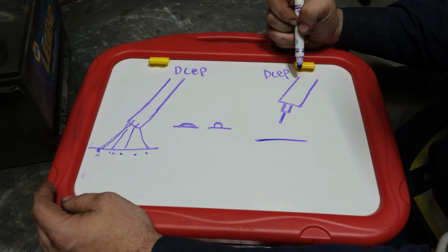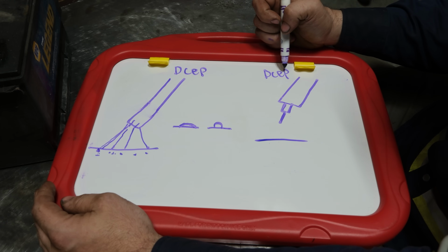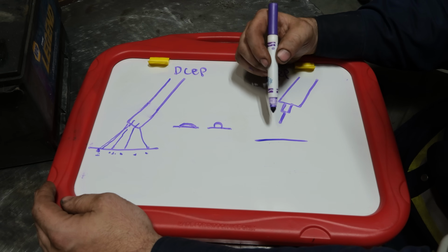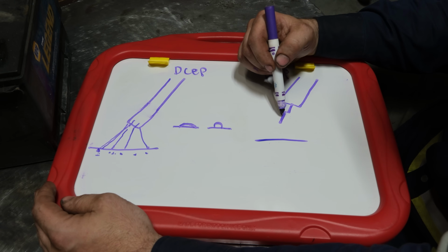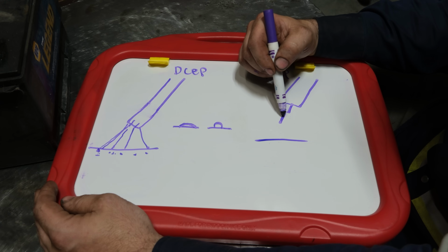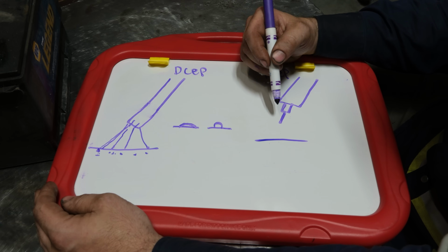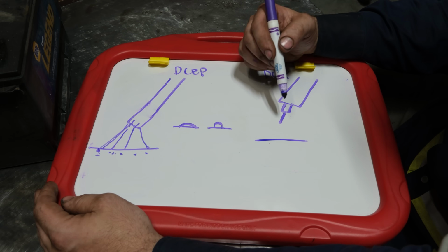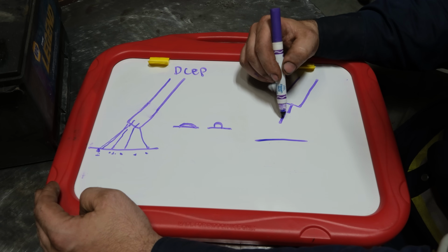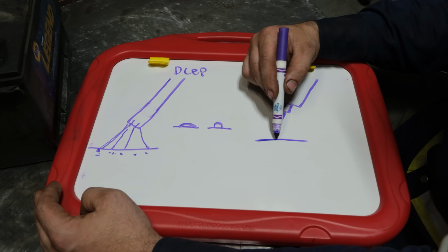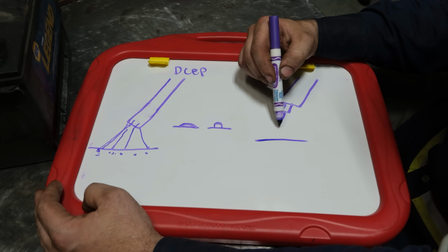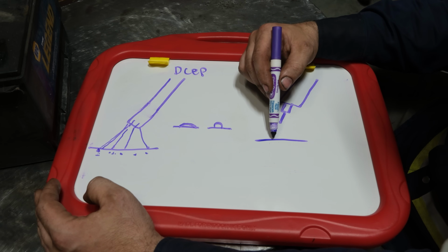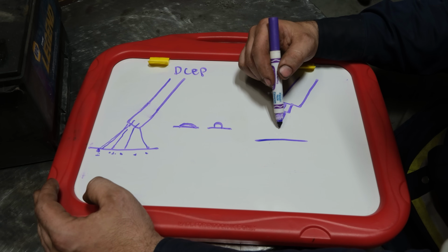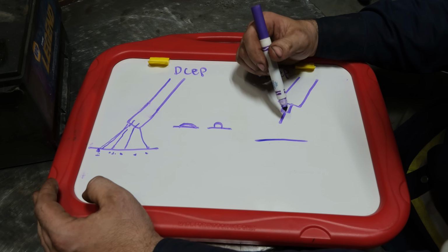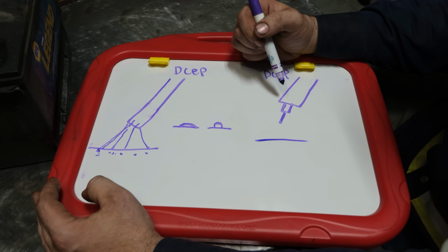So now with MIG, which is done electrode positive universally, the same effect with stick happens, where you're putting a massive amount of heat into that wire. When you get into super high voltage and gas mixtures for spray arc, that gets the wire so hot that it literally turns to liquid before it even transfers over. The standard short circuit process, the wire is a solid until it stabs that molten pool and blows apart. So spray, it's a liquid as it crosses.